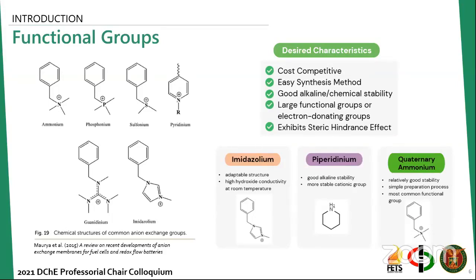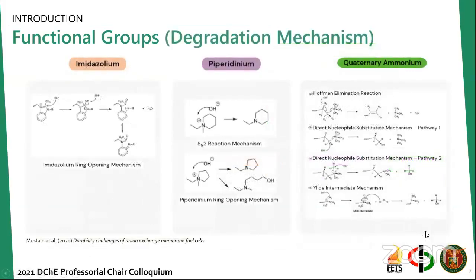So for the study, and due to data availability, the functional groups are narrowed down to three, which are imidazolium, piperidinium, and quaternary ammonium. Shown in this slide are the degradation pathways of the functional groups after exposure to an alkaline environment, since the hydroxide attack may reduce the conductivity of the membrane.